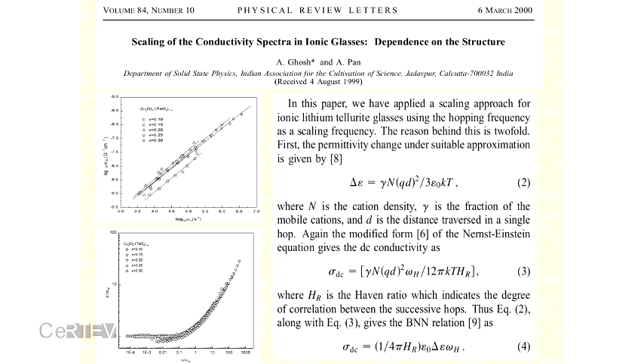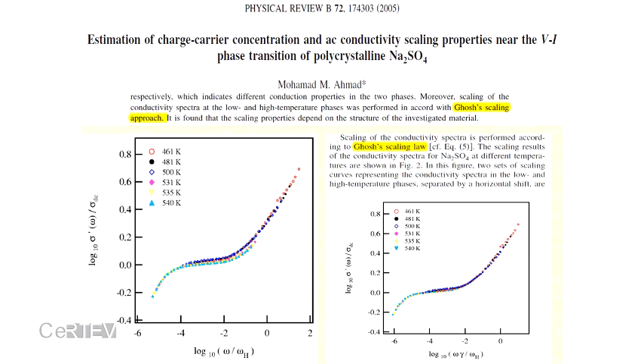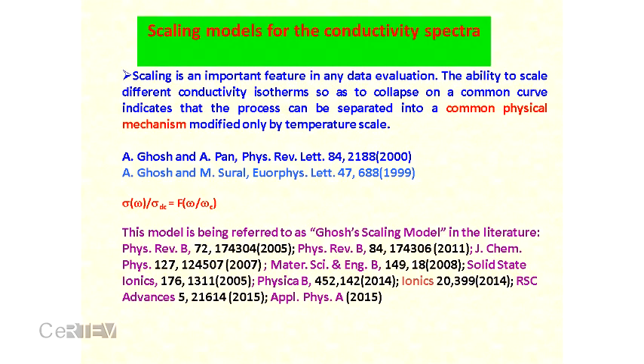In our calculations, from the consideration of the dielectric spectra, we have shown that the DC conductivity can be related to the hopping frequency. You can see here the Haven ratio, because the Haven ratio is very important in these types of glasses. When we plot the DC conductivity, scale the AC conductivity by the DC conductivity, and the frequency axis by the crossover frequency, we get the function as a frequency plot. Then we can have one common curve, which is independent of temperature as well as independent of composition if there is no structural change in a specific composition domain.